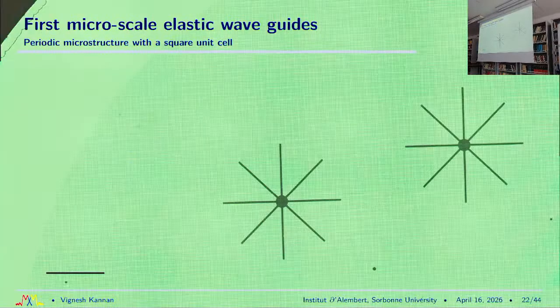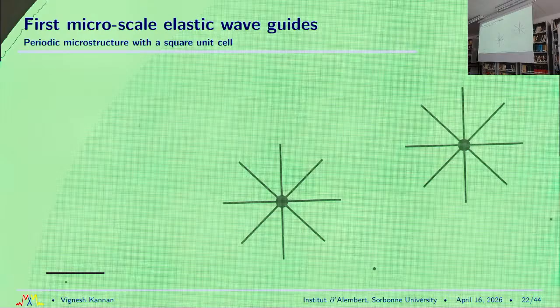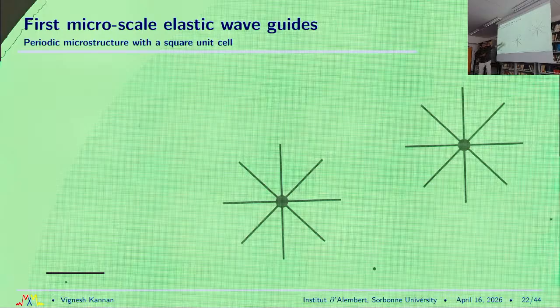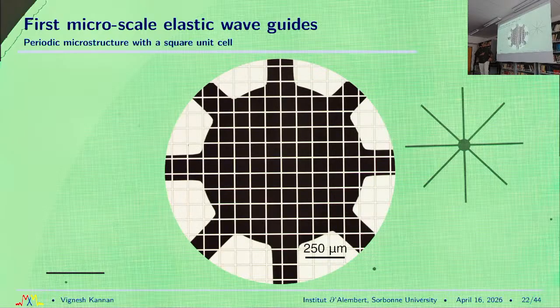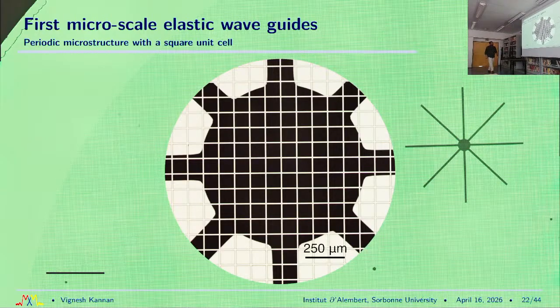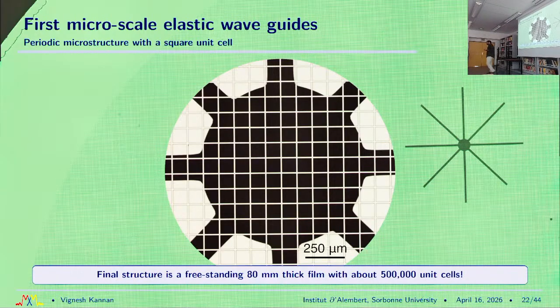So let's look at a micrograph of our samples. So what you're seeing here is the edge between the architectured region and simply the solid silicon. These are the windows at the bottom of the silicon, and if I zoom in, that's my beam, right? So I have about 10 micron beams and 100 micron unit cells, about over 600,000 unit cells, right? And the beautiful thing about these experiments is if you're careful enough, you actually end up with nearly 90 to 100% accuracy. You end up with very few broken beams as long as you're careful inside the clean room.